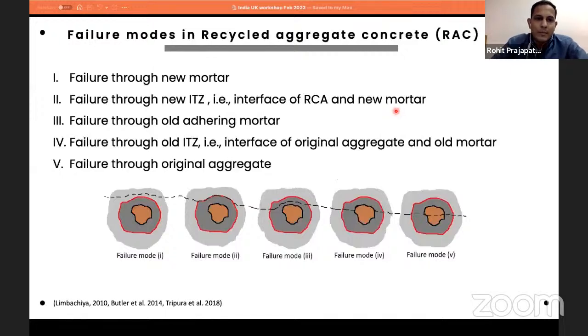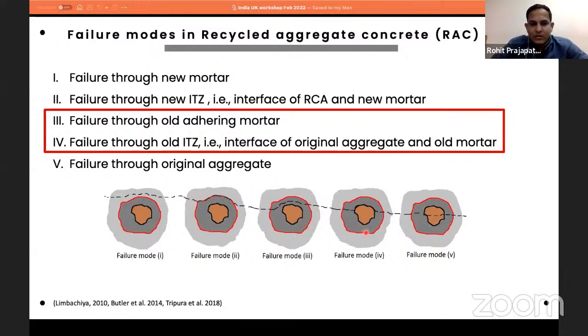And what are the main failure modes if you talk about recycled aggregate concrete? There are 5 types of failure modes. First, the crack could pass through the new mortar, or it could go through the ITZ between old mortar and new mortar, and it could pass through the old mortar itself and the old ITZ, or sometimes it can pass through the aggregate itself. Out of these 5 failure modes, 2 failure modes, 3 and 4, which is through the old adhered mortar and between the old ITZ, are more common.